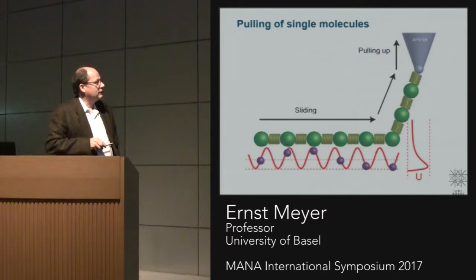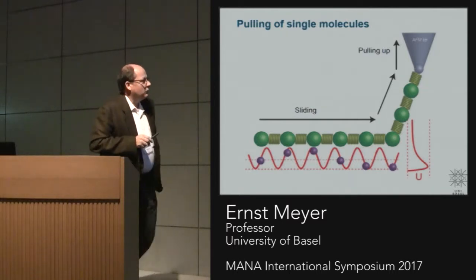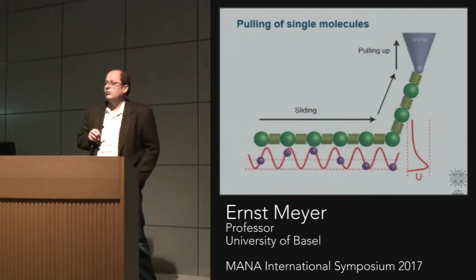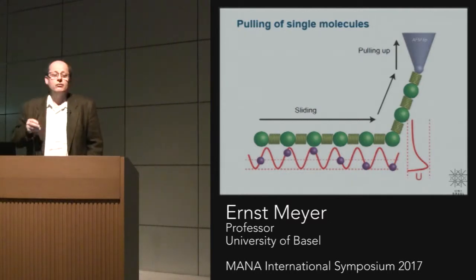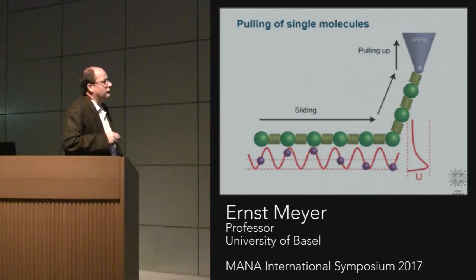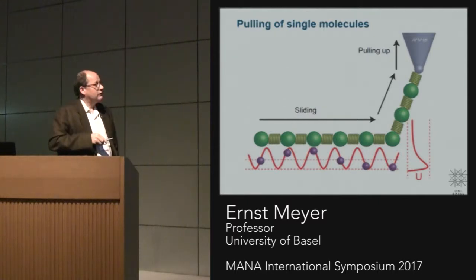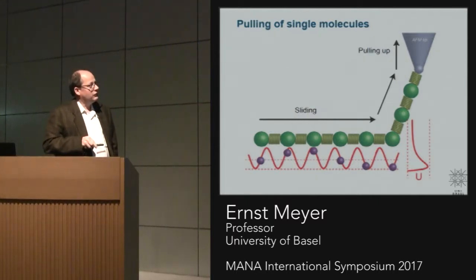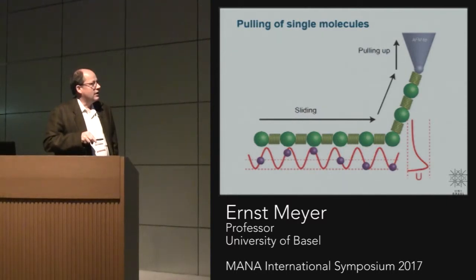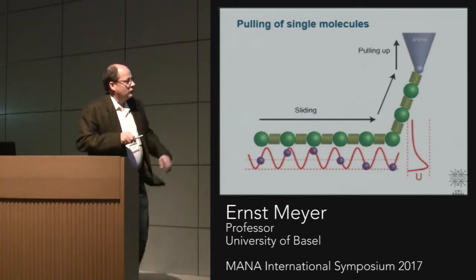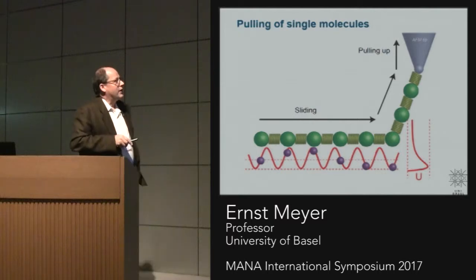So together with Alexis Baratoff, we developed a very simple model. Maybe some of you know the Frenkel-Kontorova model, which is one of the old models in friction, and this is in a way quite similar, with the difference that you basically pull on one end. So you have here springs and atoms in a way, and here you have the surface, and you see already that this is not commensurable, so we have not a completely regular pattern to expect.